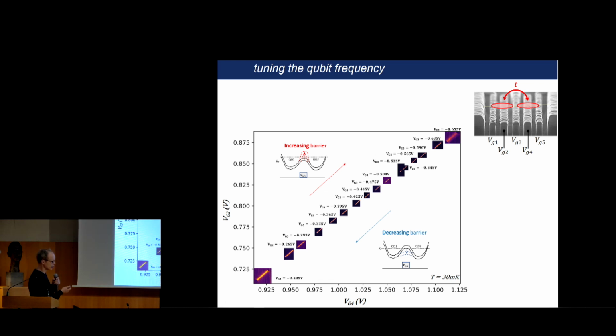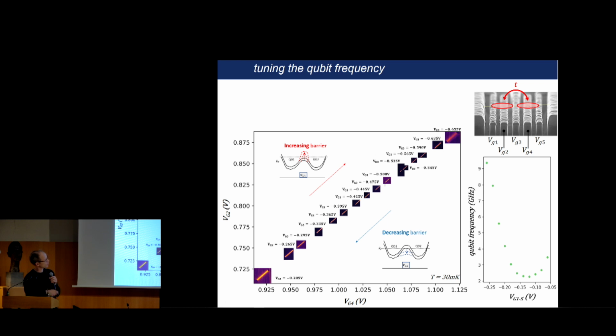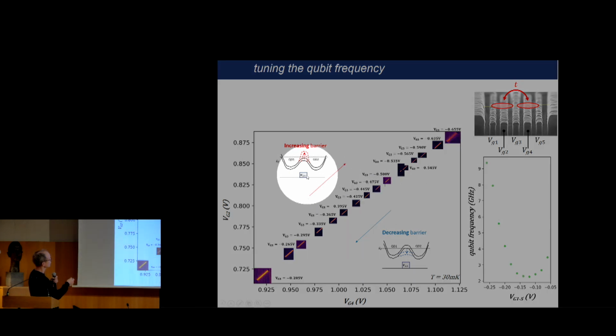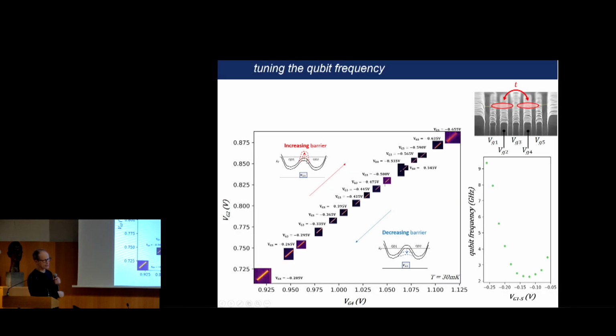We can also tune this tunnel coupling with the gates. So here it's possible to change the frequency from 2 gigahertz to more than 9 gigahertz here in this plot, but we can go above 100 gigahertz. And this is because when we play, for example, with gate 3 here, it's possible to change the position of the band gap with respect to the Fermi energy, and in this way you can change the tunnel coupling. So we have a system that we can control very well with the different gates, and where we play with one electron, we can play with the tunnel coupling, and then we couple this to the photons of the superconducting resonator.